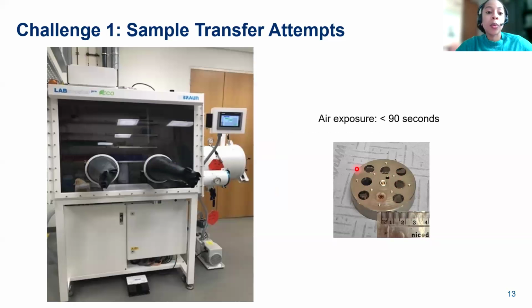So the next step was to do all of the preparation necessary to mount the samples inside of the argon glove box, which is a bit fumbly. The screws are very small and it's a bit challenging, but it was able to be done. And then after I assembled all of the samples inside of the glove box, I put it in a sealed bag, took it downstairs to the NanoSIMS, and then I was able to transfer the sample holder into the instrument in less than 90 seconds.